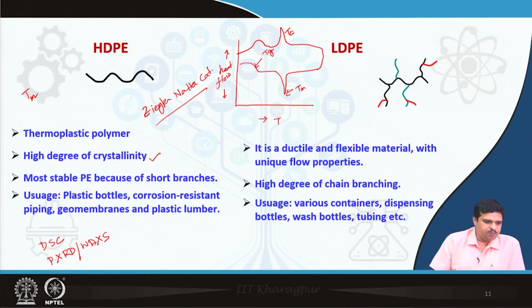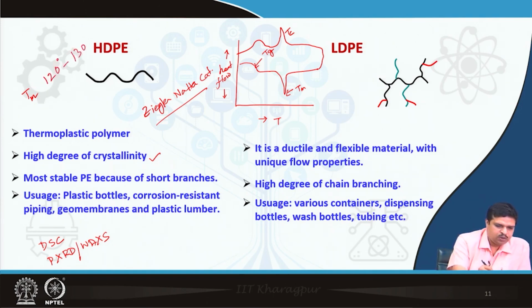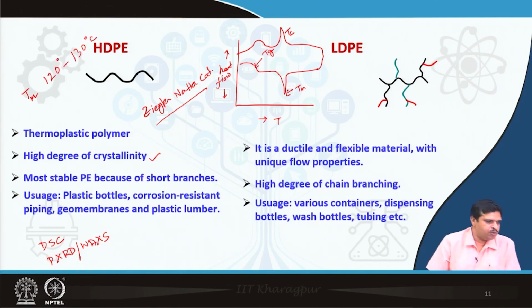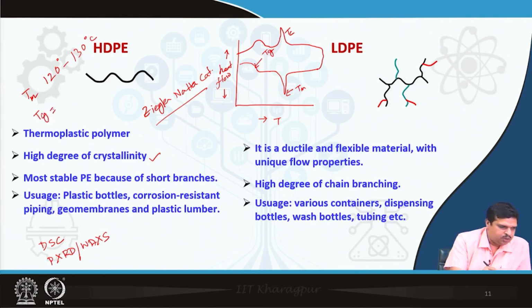So, for HDPE you will get a nice crystallization temperature if you do the DSC, okay. Here you will see for Tm you will get 120 to 130 degrees centigrade for HDPE, okay. And the Tg you will get is minus 120 degrees centigrade, okay.